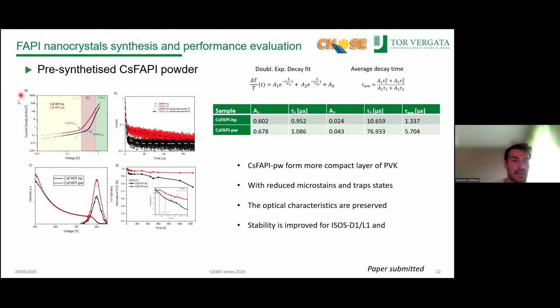From SCLC analysis, we can see that, for example, the perovskite layer from powder has less trap state density, that is also demonstrated by TRPL analysis, in which the slow component of the decay of our FAPI perovskite from powder is much lower than the high purity precursor film. In all the cases, we didn't lose any optical characteristics on the films, because even the UV-vis and the steady state PL preserve the same peak without any shift.